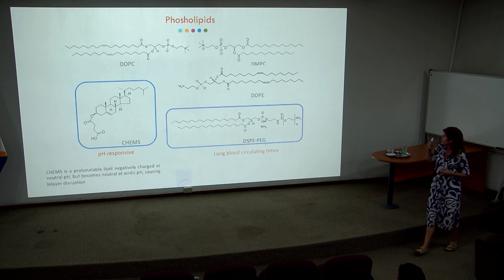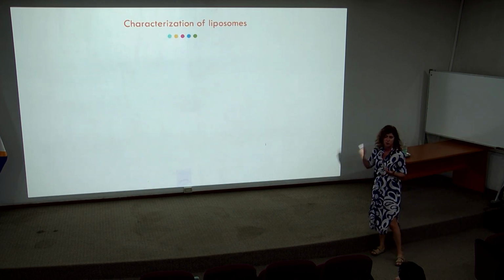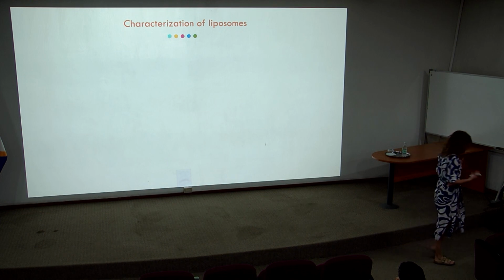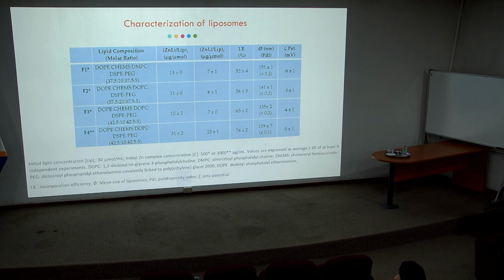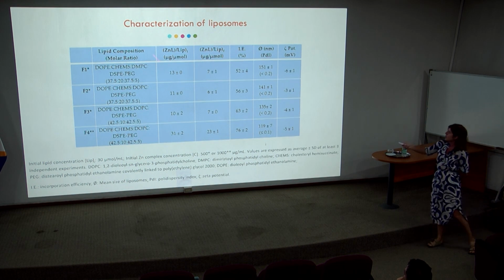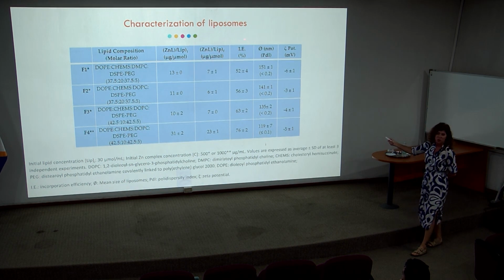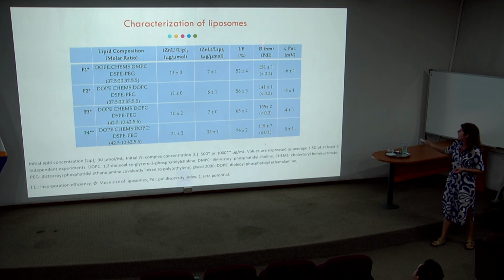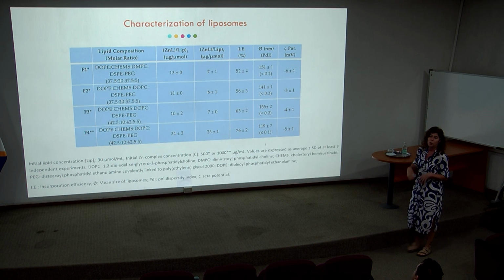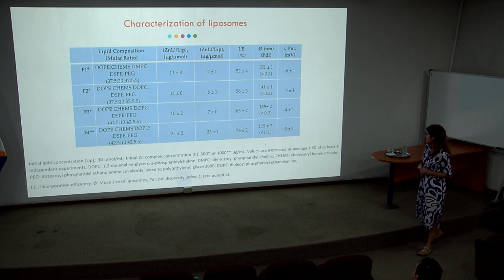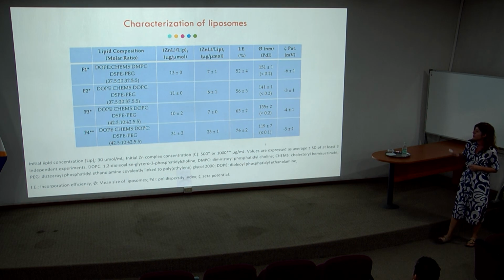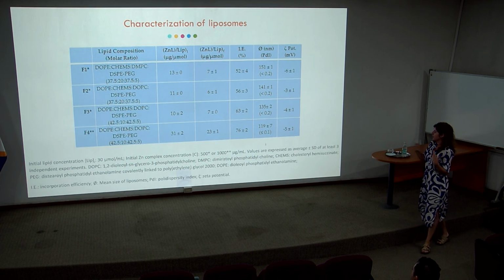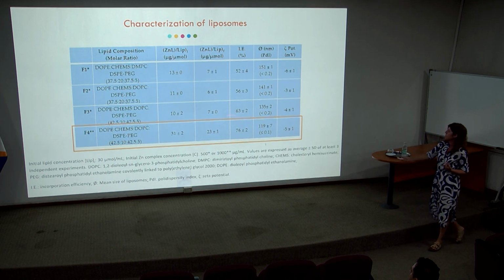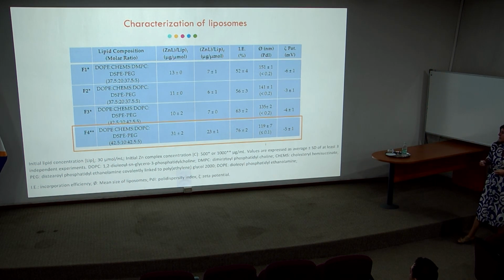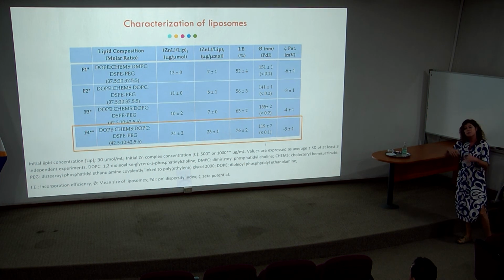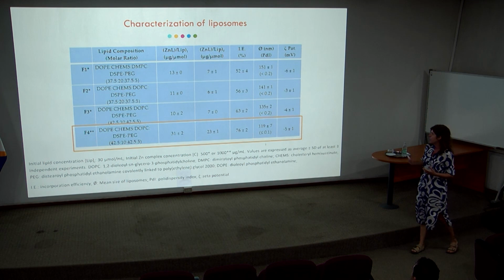I'm not going to show you much about this slide. We characterized, of course, the liposomes in many different aspects. I also have no time to go into detail, but we evaluated the incorporation efficiency, which of course should be high, the diameter, which should be below 200 nanometers, it's like the ideal size, the polydispersity, and the zeta potential. And from this list of liposomes, we chose this one mainly because it had the highest incorporation efficiency. So now we had in our hands the free compound and the compound incorporated into the liposome.